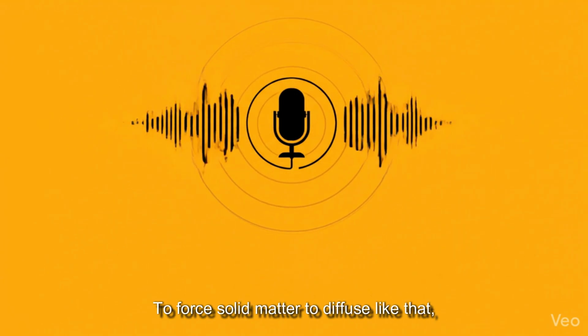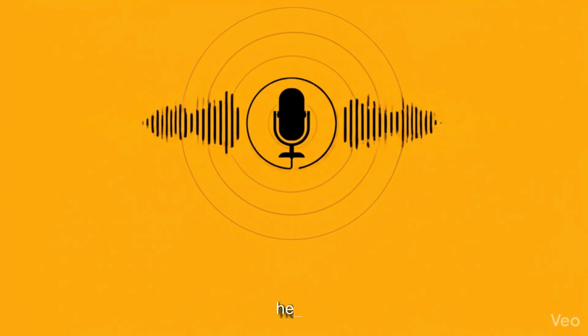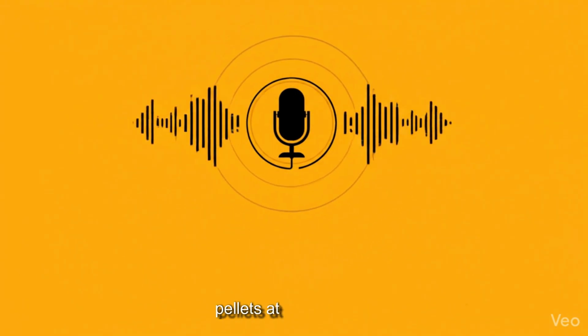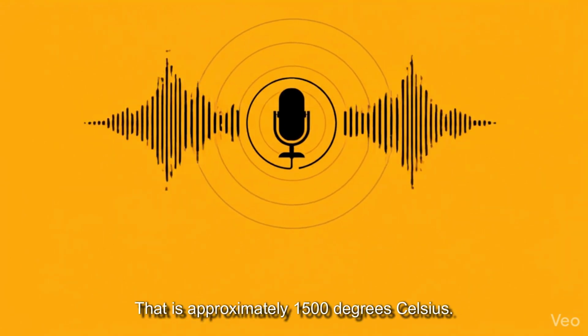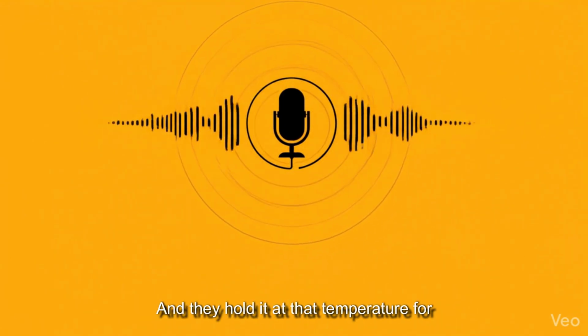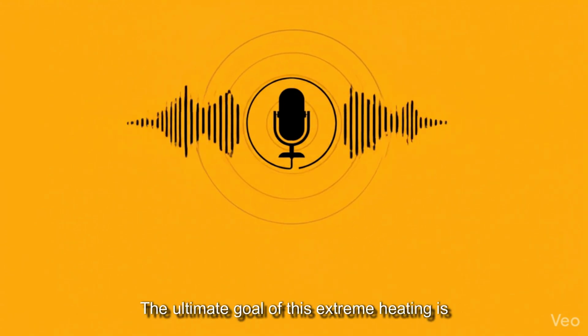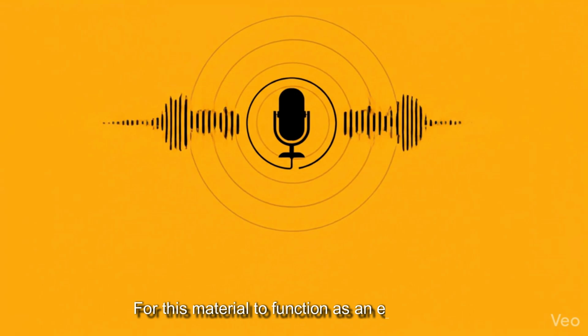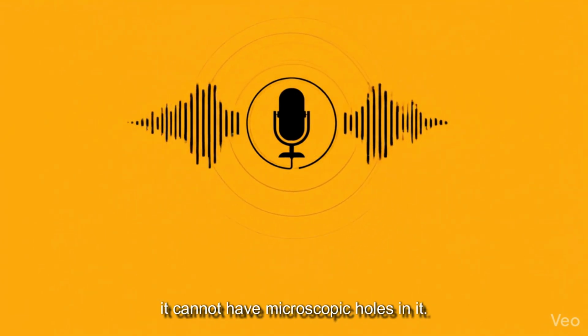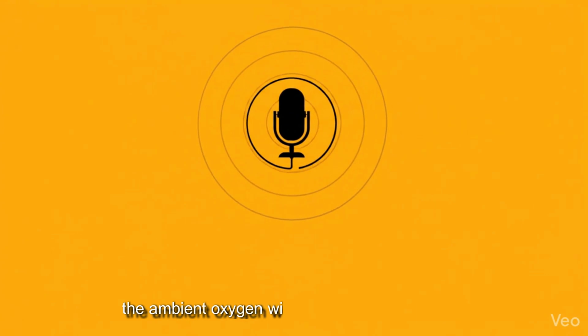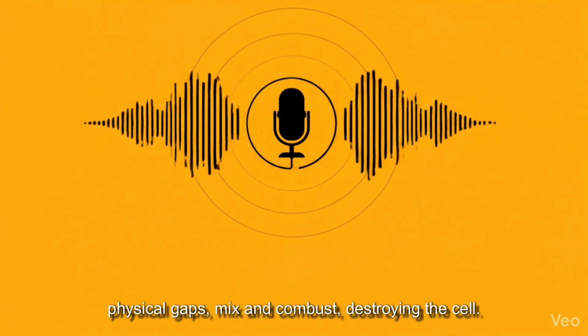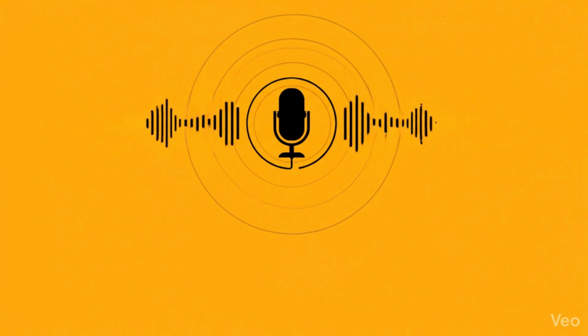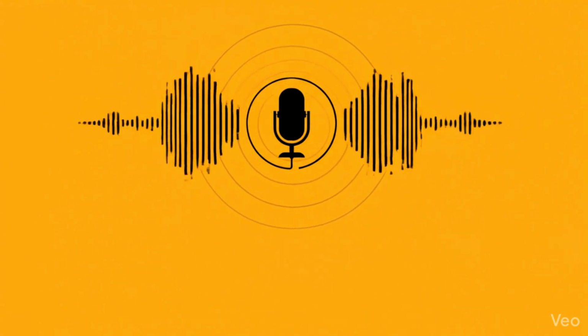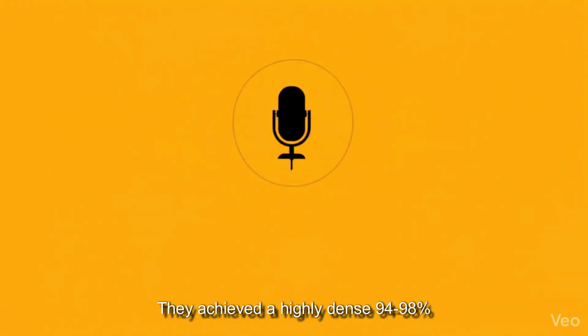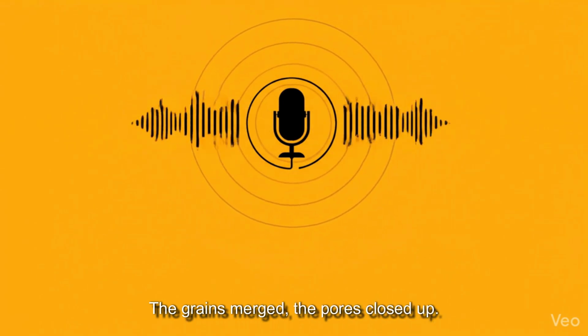To force solid matter to diffuse like that, you have to subject it to extreme, punishing heat. The thesis notes they had to sinter these pellets at 1773 Kelvin. That is approximately 1,500 degrees Celsius, and they hold it at that temperature for hours. The ultimate goal of this extreme heating is density. Okay, density. Why is that so important? For this material to function as an electrolyte, it cannot have microscopic holes in it. If it is porous, the hydrogen fuel and the ambient oxygen will simply seep through the physical gaps, mix, and combust, destroying the cell. Oh, right. Boom. Exactly. It must achieve a relative density of well over 90%. And the extreme 1,500-degree heat did the job mechanically. They achieved a highly dense 94 to 98% rock-solid pellet. The grains merged, the pores closed up.